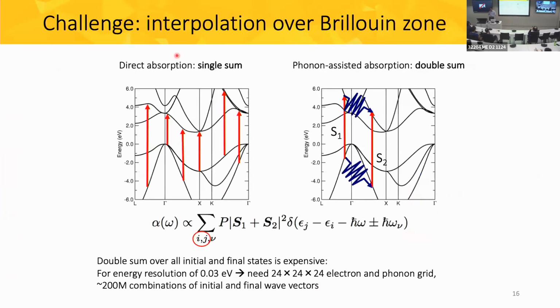The problem is that we have many combinations to take into account. So when you look at direct absorption, we just have a single sum from the valence to the conduction band. But when you have a phonon-assisted process, we need to consider every possible initial state going to every possible final state, and that number of combinations is just very large, about 200 million. So even on very large supercomputers, this constitutes a very sizable challenge.